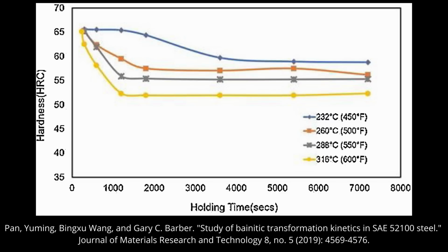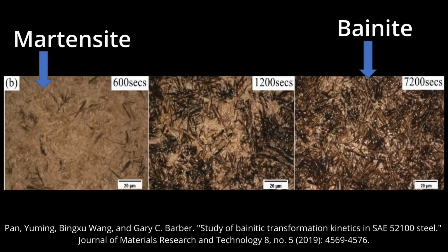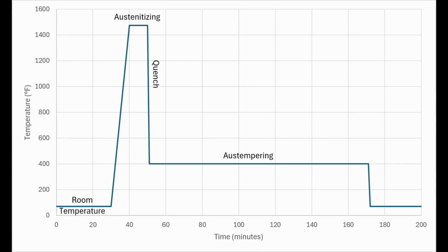Now, even if you did get a little bit of martensite that formed at the end, that is easy to take care of. That martensite is untempered, but if we add an extra tempering step, like at 400 degrees, that would temper the martensite, and there wouldn't be any brittle martensite left in the steel. That takes away one of the benefits of Austempering, that you can do it in a single step as opposed to quench and temper where you need multiple steps. But usually it's not that big a deal, so if you're concerned about not being fully transformed, you can add a tempering step after the Austemper.